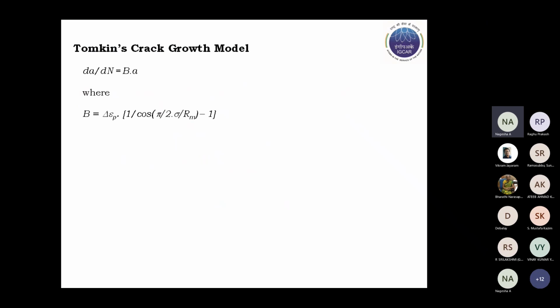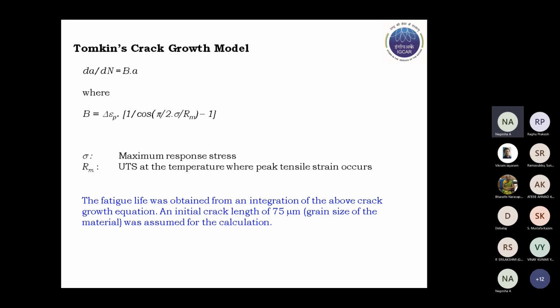Another approach that was also used is a crack growth model proposed by Tomkins, where the crack growth rate is represented as B into A, where B is given by this expression as a function of the stress and the plastic strain. Sigma is the maximum response stress, and Rm is the UTS at the temperature where the peak tensile strain occurs. For this calculation, we have assumed an initial crack length equal to the grain size. These approaches were used for 316LN stainless steel, which had a grain size of 75 microns. So this was assumed for the initial crack length, and the final crack length was taken as 1.2 mm.